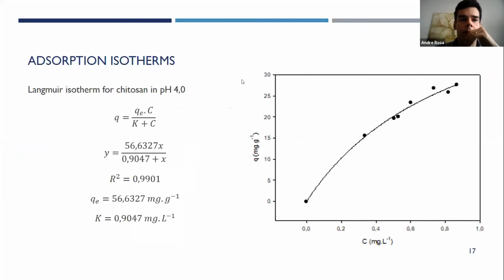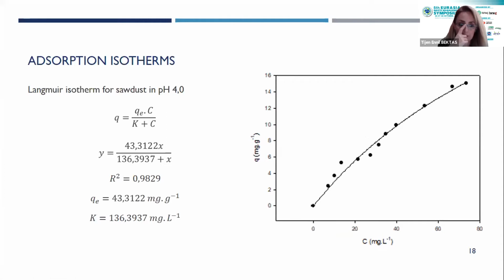At pH 4, the Langmuir isotherm for Chitosan shows an adsorptive capacity of 56.6327 milligrams per gram and a balance constant of 0.9047. Being lower than 1, these constant values show that the adsorption rate is higher than the desorption rate. Sawdust at pH 4 shows an adsorptive capacity of 43.3122 milligrams per gram and a balance constant of 136.3937. Although the adsorptive capacity increases with the decrease of pH, the desorption-adsorption rate increases even further, showing that the desorption rate gets higher with the decrease of pH for sawdust.